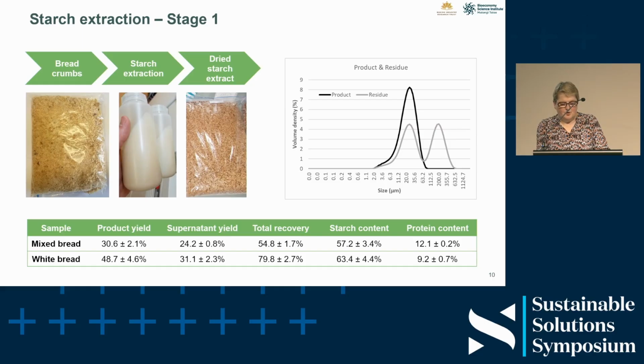The graph on the right, on the bottom axis, is the particle size. So the dark, higher peak, that's the sort of scale of the original product, and then to the right just shows that the larger particles, that was mainly the fibre that was able to be sieved out. Then what is quite important here is if you look at the total recovery, when we had the mixed bread crumb as a base, there's a lot of larger particles in that, so we got 55% recovery, and with the white bread it was 80%, because that's obviously got a lot lower fibre content.